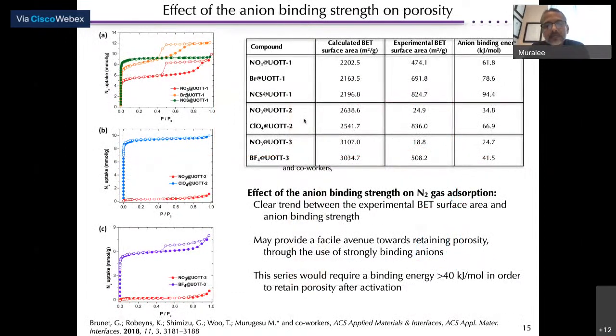So this seems to be working well, but what about the porosity and the stability of this system? This was done in collaboration with Professor Shimizu in Calgary, because we didn't have at that time our own setup to do this. What we can see here, when it comes to the nitrate frameworks, the BET surface area shown here is much lower than the predicted or calculated one. In all of these cases, this is a bit disappointing. That tells us it's not very stable.